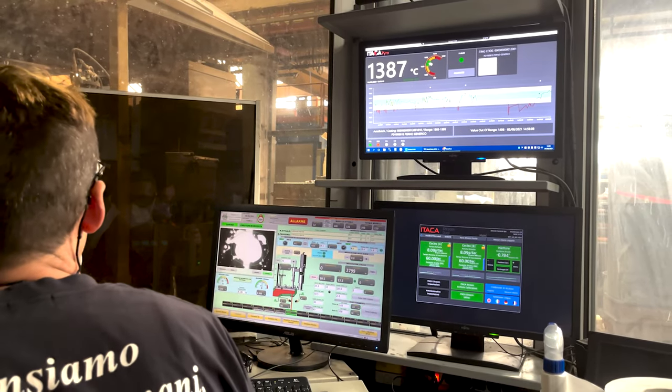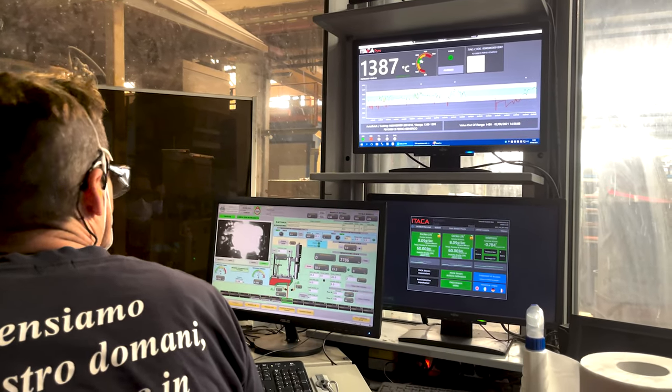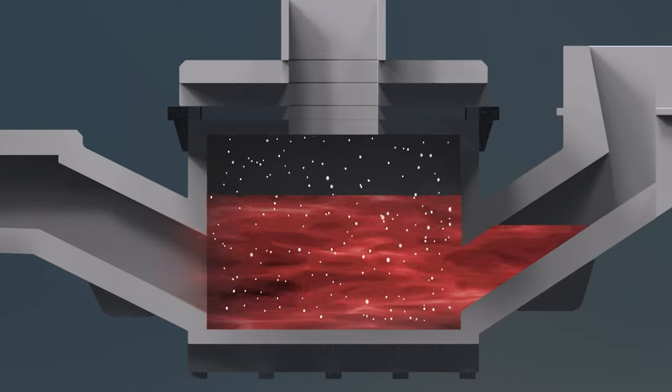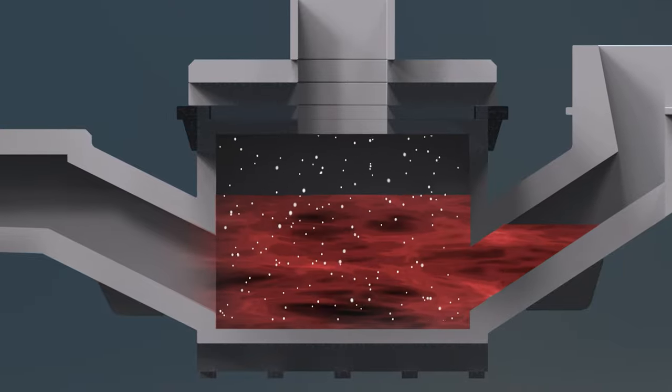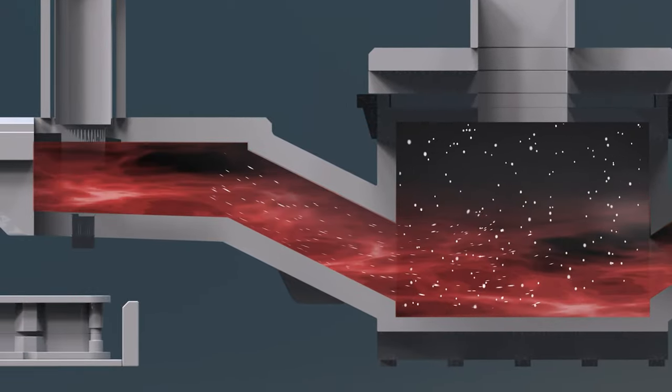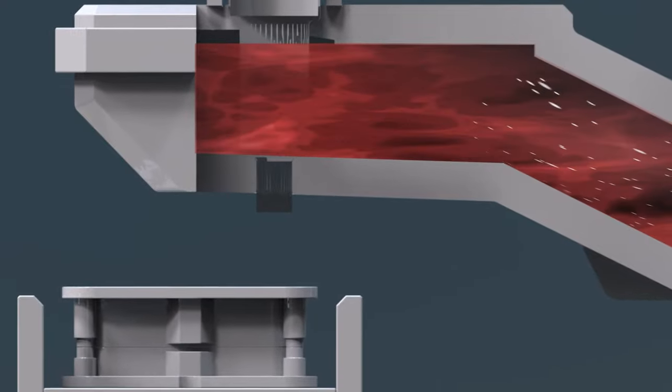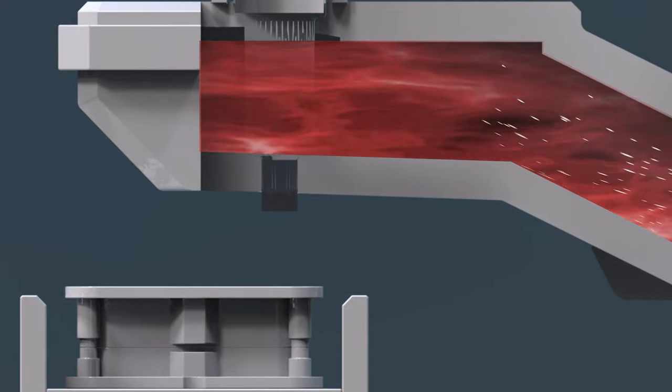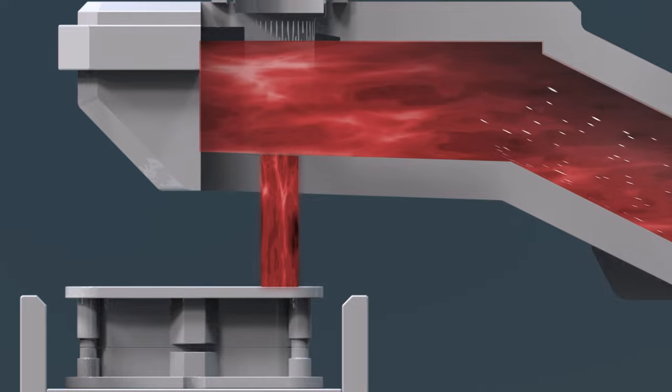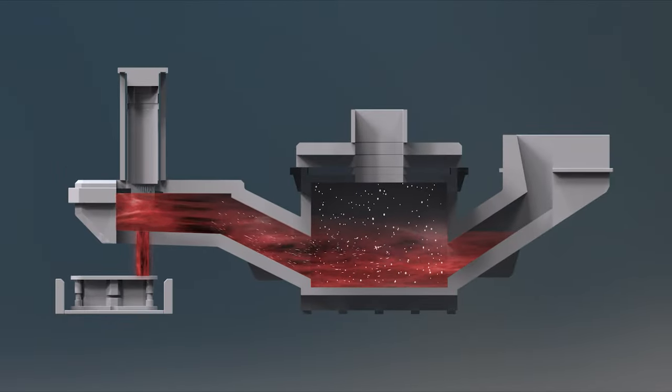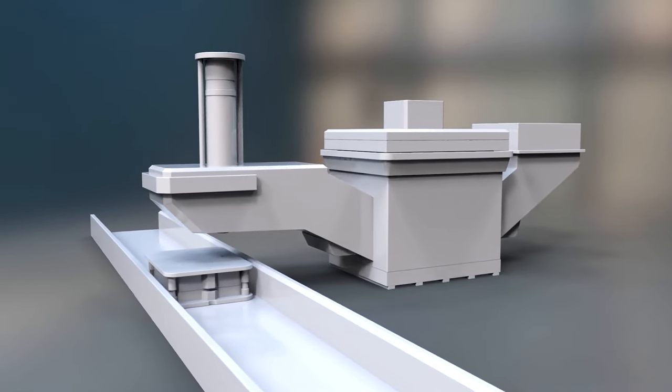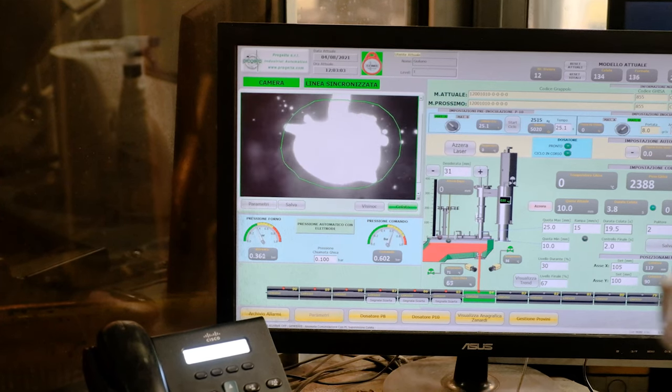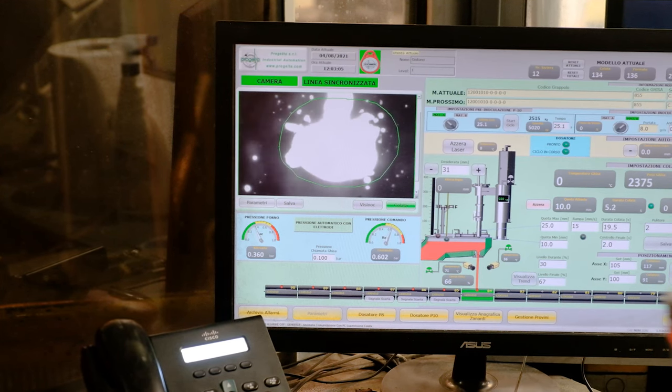Let's see in detail the various components. The metal inside the main room is kept in a modified atmosphere using nitrogen and forced to rise inside a canal exposed to atmospheric pressure, at the end of which is placed the nozzle, which acts as a regulating valve for the control of the liquid cast iron flow when filling the flask below. The casting ladle has a maximum capacity of 4,500 kg and is equipped with cameras to control that the nozzle opens to let the liquid cast iron flow.